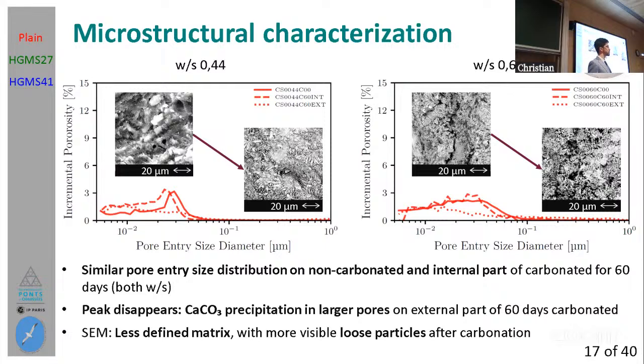There you will see the solid line that corresponds to the non-carbonated cement paste. Then the dashed lines correspond to the samples carbonated for 60 days in the internal parts, meaning these less affected parts. And then we have the dotted line, which is down there, which corresponds to the sample carbonated for 60 days on the outer parts. And what you can generally see there is that both the internal part of the cement sample carbonated for 60 days and the non-carbonated cement sample present roughly the same kind of microstructure.